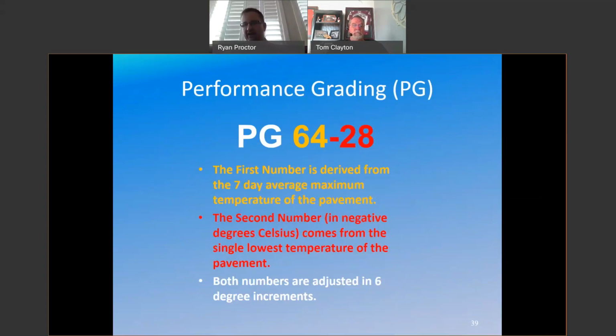I mean, the fatigue cracking is more of a long-term effect, but if you're going to see rutting, it's generally in that time frame. The second number is in negative degrees Celsius. It's not a dash, it's a negative value, and it comes from the lowest single temperature of the pavement. When I talked about those DSR tests, I skipped over the temperatures. When I talked about the BBR test, I skipped over the temperatures. You run those DSRs for this binder at 64 degrees Celsius. And for the BBR, as I mentioned, it's complicated, but you would run it at negative 18 Celsius.